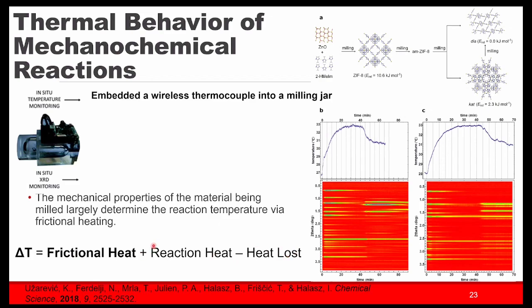And then you have the heat of the actual reactions. But what was really interesting, at least in this case, and I think this is partially because the change in energy of these phase transformations isn't huge, is that this frictional heating is going to be highly dependent on the sample that's in the milling jar. If you think about it, frictional heating, the question is how inelastic or how elastic are your collisions and how much heat is being absorbed. If your sample can absorb a lot of the energy of the milling process, the temperature is actually going to be higher. And I thought this was quite interesting and really quite striking.